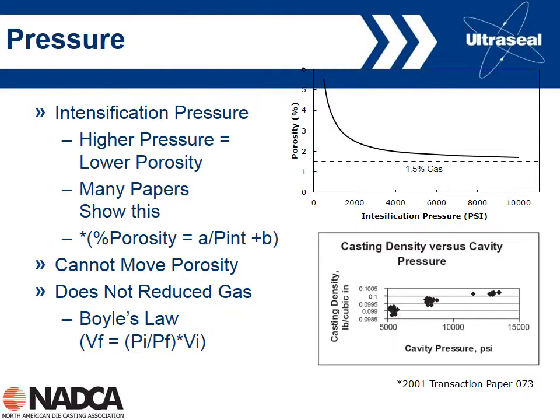What it shows is what we were talking about earlier: the porosity content initially decreases with an increase in pressure. But once you get to, I don't know, maybe 3,000 psi or so, we don't see a tremendous additional drop in porosity content as we go to higher pressures. We have some effect, but not as big as initially. The lower graph here shows some real data. This is looking at the density of die castings, i.e., we increase the density as we get a decrease in porosity because we're getting rid of the holes, and so we see a slight increase in density